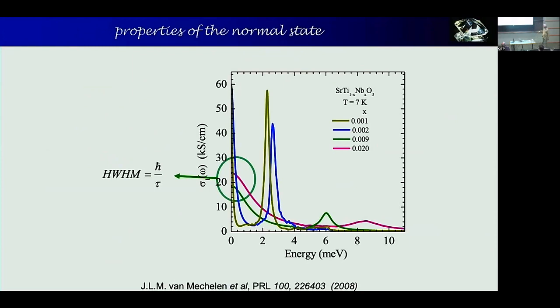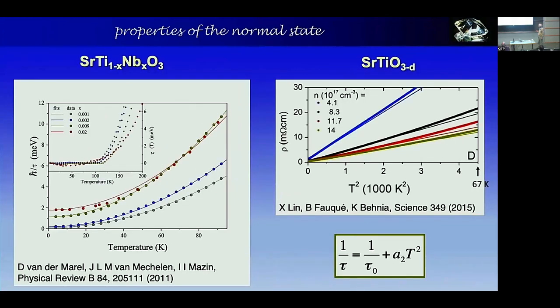Okay, so I'll say a bit more about this mass enhancement, but there's another piece of information you also get from the Drude peak. The width is proportional to the quasiparticle lifetime in a simple quasiparticle picture, if you have quasiparticles. And so we can just take that width and plot that as a function of temperature that is shown over here for 4 different dopings. And so the dots are just the width, the way it is measured from the optical data.